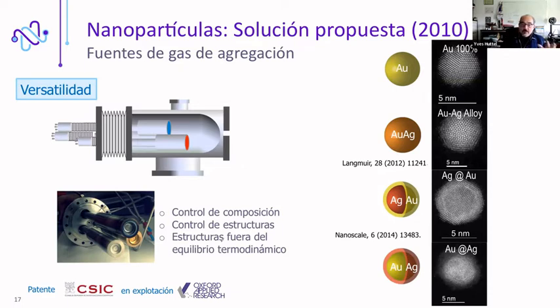So thanks to this modification of the cluster source, we are now able to make nanoparticles with controlled chemical composition, because the density of the plasmas can be controlled by the voltage we apply to each magnetron. So we can fix or modify, tune the density of atoms of one element during the formation of the nanoparticles. We can control the structure, as we can make core shell nanoparticles. And this allows us to make nanoparticles that in principle are not available with other fabrication methods. So this patent was licensed to Oxford Applied Research, and it is still running.